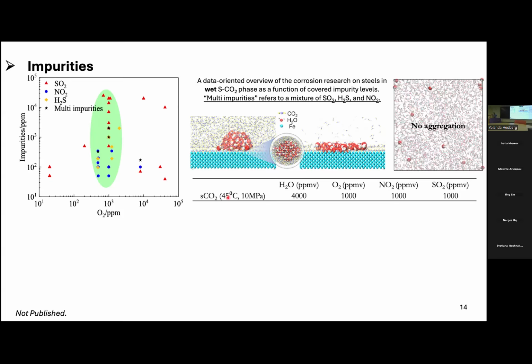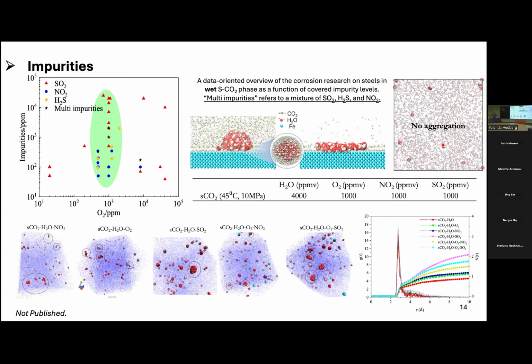So if it's, for example, 45 degrees C and 10 megapascal, the water saturation value is about 4,600 ppm. If we choose 4,000 ppm, which is a little below the saturation value, ideally there should be no aggregation of water. So water molecules are evenly distributed in the CO2 box. Why the other impurity works is that it will facilitate the water aggregation. So water will form molecules, then splash and form a layer.